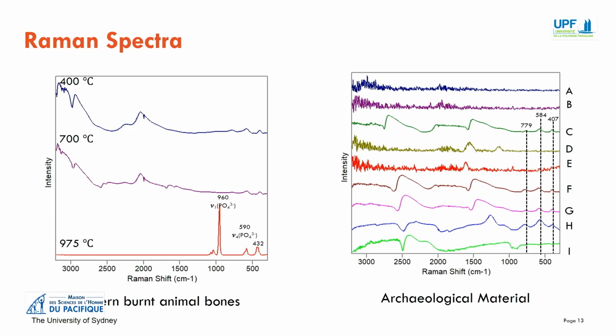In addition to portable infrared spectroscopy, similar data were collected using a handheld Raman system. The data from the reference samples are provided on the left-hand side and the archaeological material on the right-hand side. The spectral quality for the data collected from the samples at 400 and 700 degrees Celsius is very poor, and this is attributed to the fluorescence of the organic material within the bone, and it was a phenomenon that was also observed by Marquis.